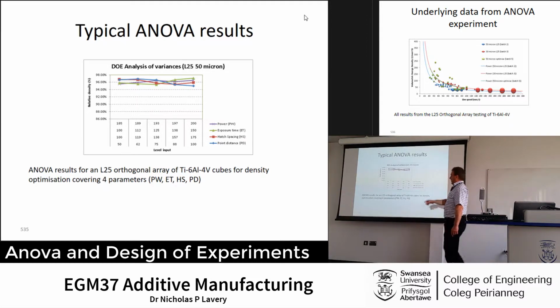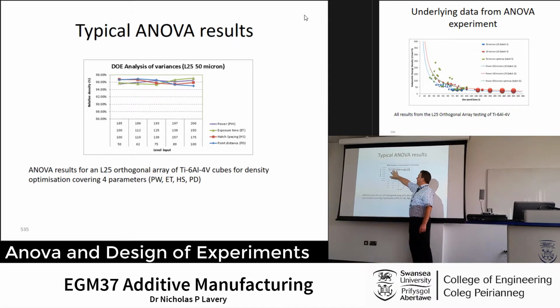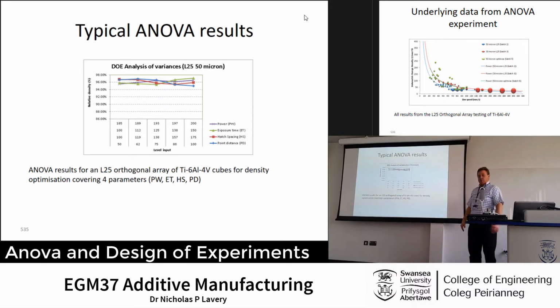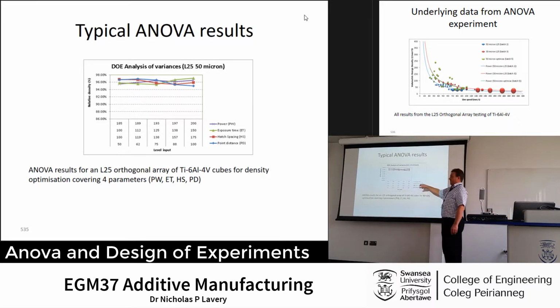Sometimes you see weird things coming out from this, which you then would confirm going back to metallography or your understanding of the melt. So one of them, for example, was hatch spacing. Now over the range, there's not a massive amount of difference here on the range of values that we picked there. But what we have found sometimes is the hatch spacing. And remember I was telling you about the hatch spacing, that you can have no overlap at all, or you can have it slightly overlapped or remelting itself at each stage.